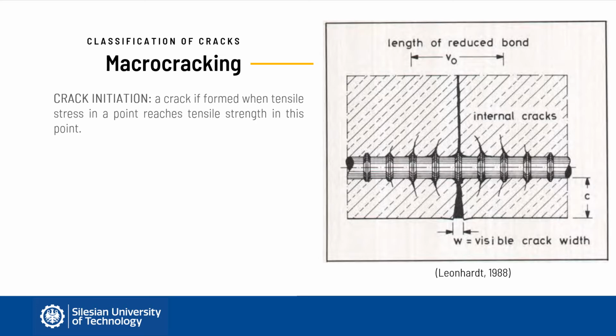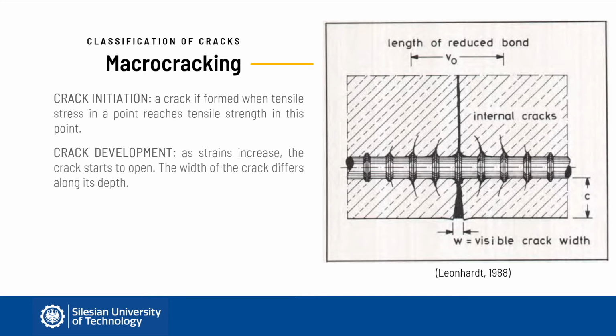Concrete is not a homogeneous material, and the so-called weakest link governs the crack formation process. It is one of the challenges in modeling of reinforced concrete to define the tensile capacity in a sense of crack resistance of concrete. As strains in the element increase, the crack starts to open.